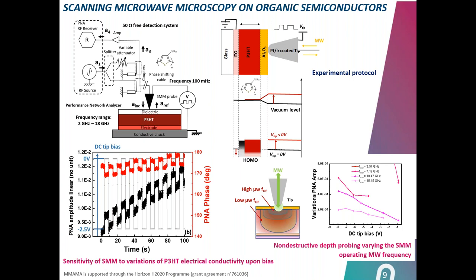to observe the sensitivity of the system, which is a Keysight SMM equipped with an interferometer, to obtain a 50 ohm free detection system. And by applying low frequency bias, we could detect the variation of electrical properties, in this case of poly-3-hexylthiophene, which is a standard material used in organic photovoltaics. And by varying the frequency, we could also probe different depths, allowing for three-dimensional measurement of the electrical properties of these materials at the nanoscale.